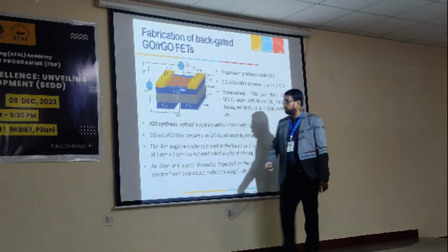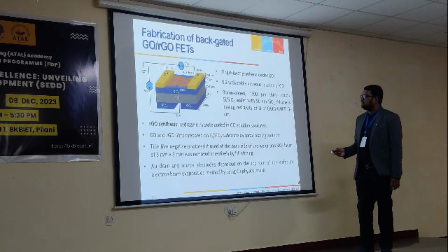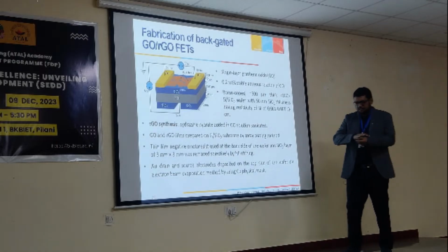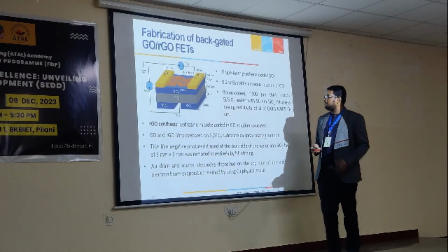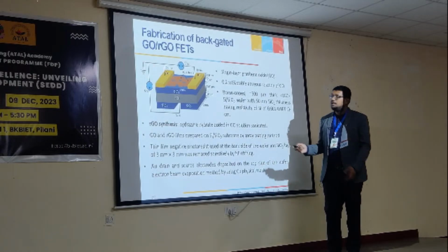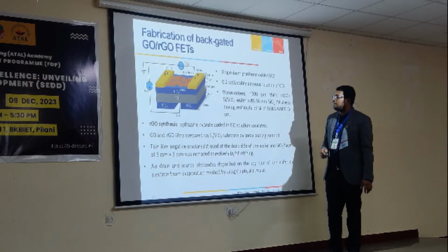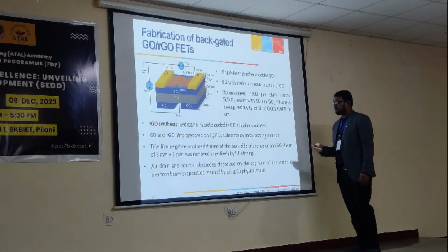Okay. Now we have etched this portion from the back side with hydrofluoric acid, and then this portion has been opened. And now on the top side, we have deposited reduced graphene oxide. These are in flake form. Graphene oxide is not a continuous layer, it's flakes. I will show you the FESEM image. So we deposited it by the drop casting method. It's not continuous, but there is connectivity from the source and drain terminal. Then after deposition of this film, we use a shadow mask to deposit the gold drain and source electrodes. So this is the drain and this is the source. Depending on the bias, one can choose which one will be source and drain.